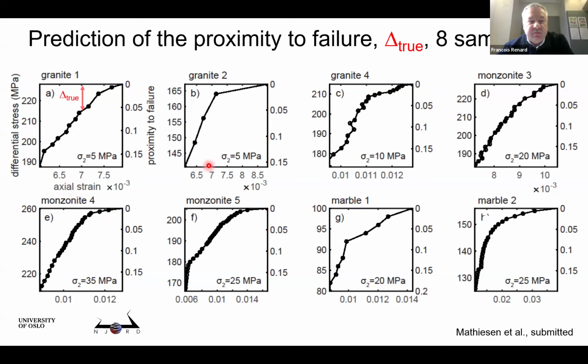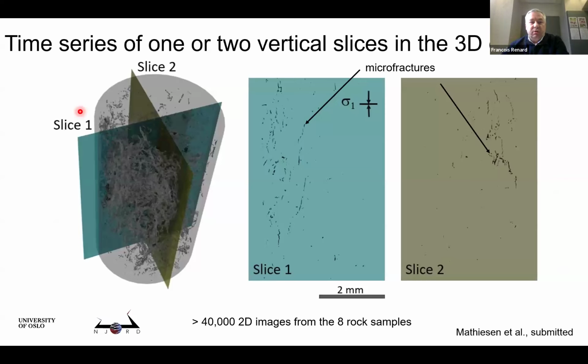For some samples, we have a lot of data. For some samples, we have only 3 or 4 of these data. And what we want to predict is this distance. So in other words, if we have a rock sample here in which we can image all the fractures, we start with a volume like that. That's a rock sample where there is a 1 when there is a fracture and 0 when there is no fracture. Let's take 2 slices in this 3D volume, and that's what we get. In this sample, the axial loading is vertical, and those are the fractures, the black dots or the black lines in 2 perpendicular slices.